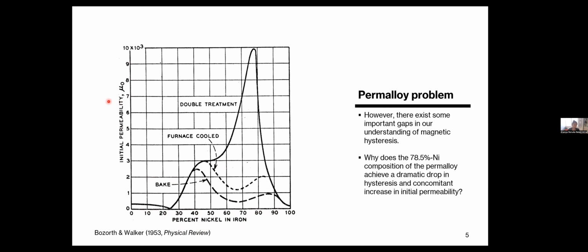What you see on the y-axis is a measurement called permeability, which is inversely related to your coercivity. So if you see a peak on this plot, showing the highest permeability, it means that is the composition that has the smallest hysteresis. What they found was that, based on the percentage of nickel present in iron, you can have magnetic alloys that show a range of these coercivities. The softest magnet they identified was at 78.5% nickel content. That's a composition that today we call Permalloy, and it is one of the well-known soft magnets that's technologically relevant and important today.